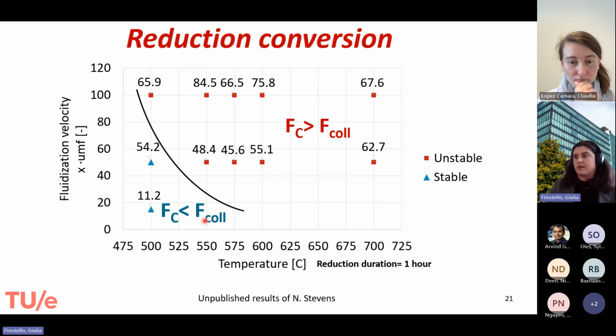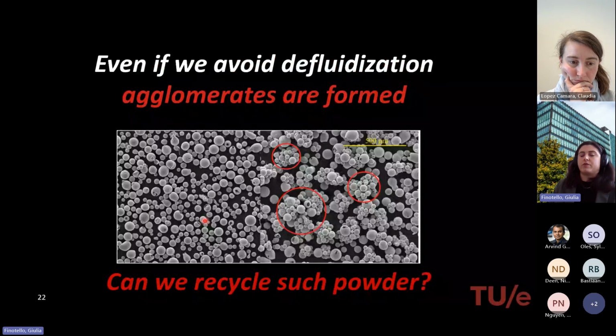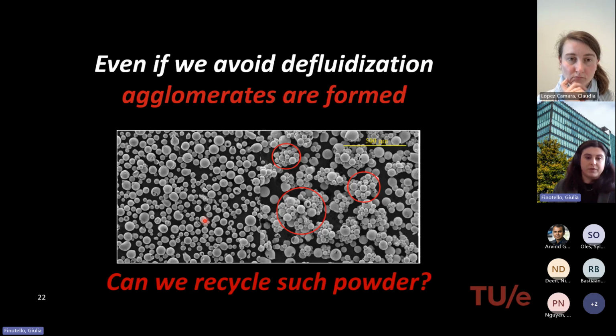So then we see that indeed we can avoid defluidization only if we stay at very low temperature. However, even if we avoid defluidization, agglomerates or clusters of particles are formed. At the level of the particle, we always form some agglomerates. So the question then was, can we recycle such a powder? Because our powder needs to go through a cycle of combustion and reduction. Can we handle this powder in a way that we can perform multiple cycles?